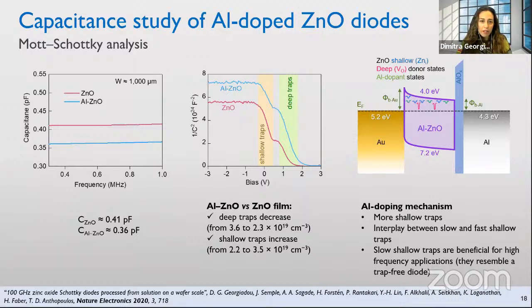Capacitance, as I explained in the very beginning, is very important to radio frequency applications. And for this reason, to fully characterize our diodes, we performed capacitance studies to compare the zinc and the aluminum-doped zinc oxide diodes. The doped diodes demonstrated a lower capacitance, although both types of devices gave capacitance below picofarad. And the fact that the aluminum-doped devices had even lower capacitance gave us an indication that they would be beneficial for high frequency applications.